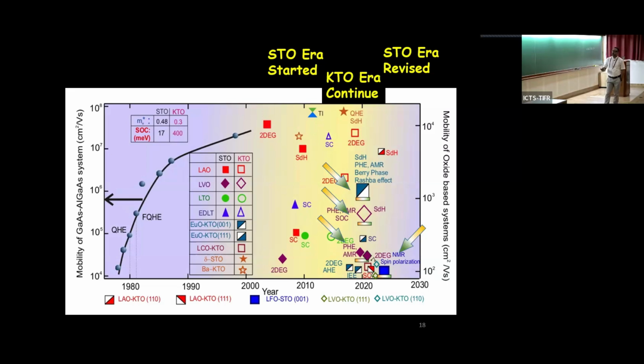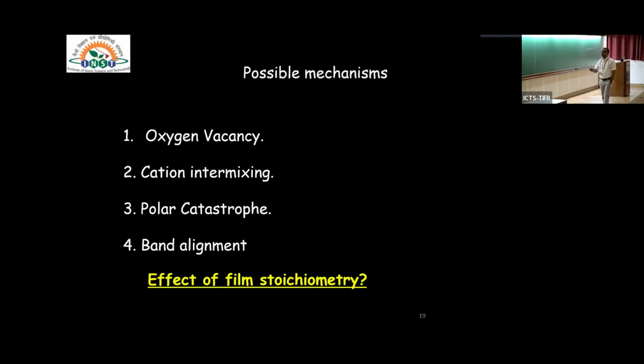But there is a scenario change around 2002, when people saw this kind of appearance of a conducting interface in oxide material, namely lanthanum aluminate and strontium titanate. Then around 2020 onwards, people have started seeing a jump from the strontium titanate based system to a potassium tantalate based system. Why is it so? Because in potassium tantalate, the spin orbit coupling strength is almost one order of magnitude higher. So you can see the effect of spin orbit coupling in the system if you can make an interface and get conductivity at the interface. After that, if time permits, we'll talk about the revisit of the strontium titanate system, where we have seen some very interesting physical properties. So when we talk about this kind of interfacial conductivity in perovskite based materials, there are 4 possible scenarios.